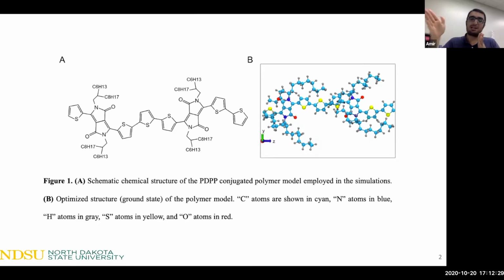But for the rest of the calculation, especially the ground state, we just rely on the PBE functional to do some not quantitative study, just some qualitative research on the excited state of this polymer, for instance, via spin polarization, via doping, either N doping or P doping, and also promotion of an electron with the Fermi calculations. So PBE functionals are more available and computationally less expensive for this purpose.